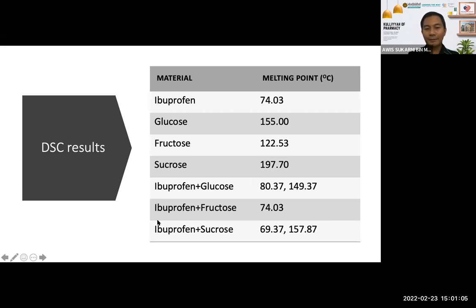And for the ibuprofen and sucrose, the melting point of the ibuprofen shifted down to 69 degrees, and the sucrose shifted down to 157 degrees.